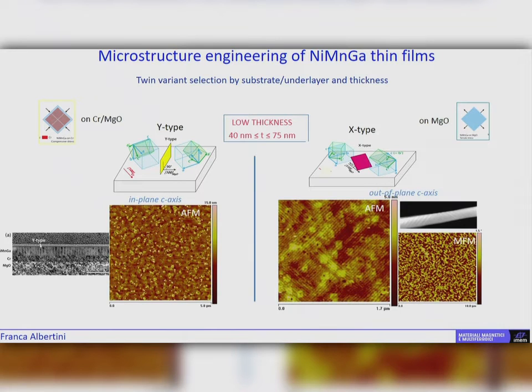As for the microstructure engineering, we have exploited the substrate, and in the case of chromium MgO, we have exploited the expansion due to the substrate, and in this case, we can select a kind of twins. In this case, it's a Y type of twins, and in the Y type of twins, the magnetization lies in the plane of the film. So by selecting the twins and by exploiting the flexibility of the martensitic microstructure, we can select the orientation of magnetization. This is for thin films.